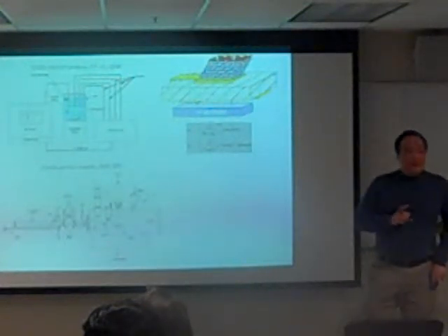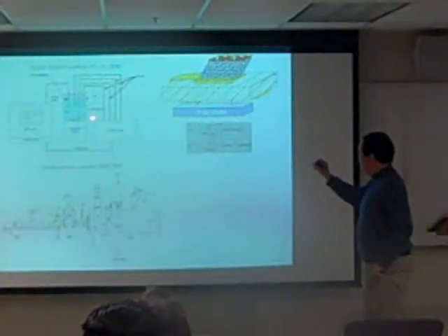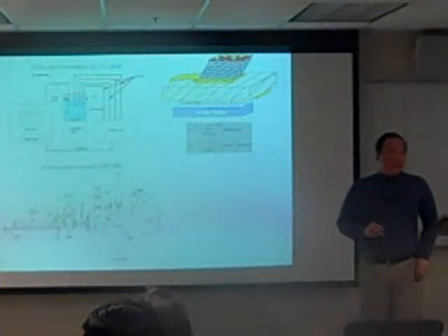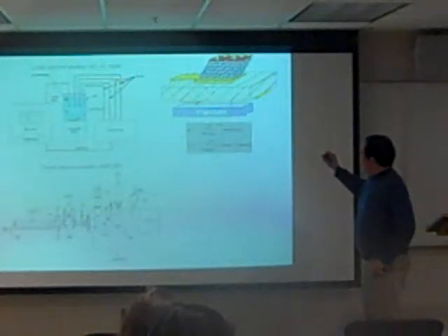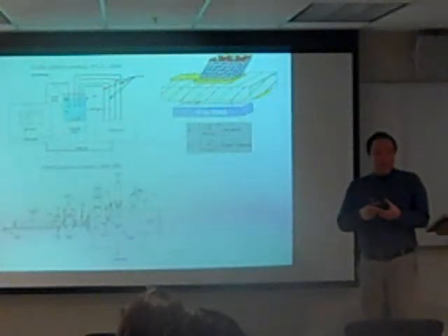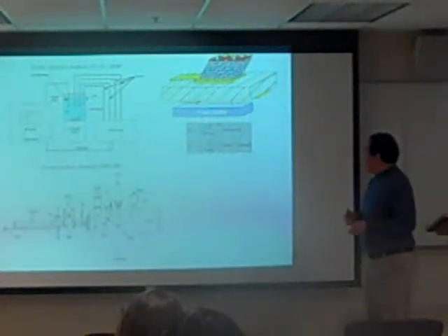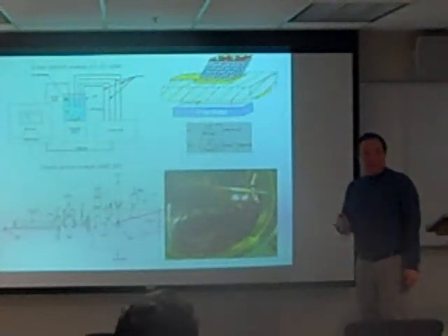And again, we relied on our surface analysis techniques. Another thing that we did, in terms of monitoring the nucleation growth of material, is we used a quartz crystal microbalance. So basically, this monitors the change in the mass. The change in the mass corresponds to the growth of these materials on that surface. So with the quartz crystal microbalance, we can monitor change in the nanogram regime, and we also couple this with our electron spectroscopic analysis and SIMS analysis as well.